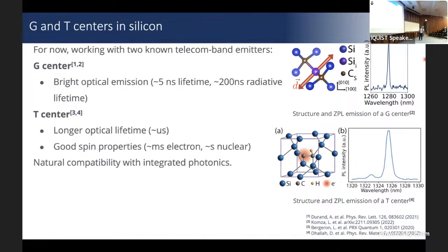And more recently, we transitioned to working with T centers. This is a more interesting system because it has a strong radiative transition. This time the radiative lifetime is about 1 microsecond, so it's not as fast. It's somewhere in between traditional color centers and rare earths. But it has good spin properties, with millisecond electron spin coherence and up to a second of nuclear spin coherence.